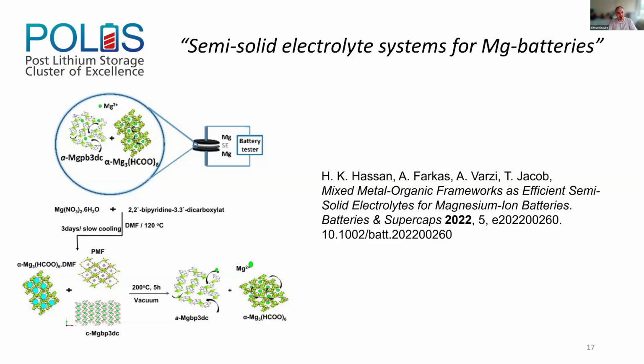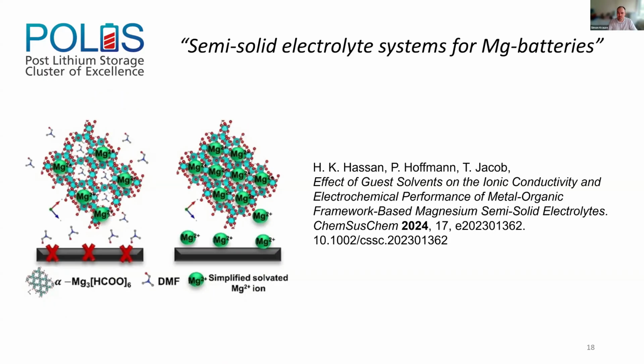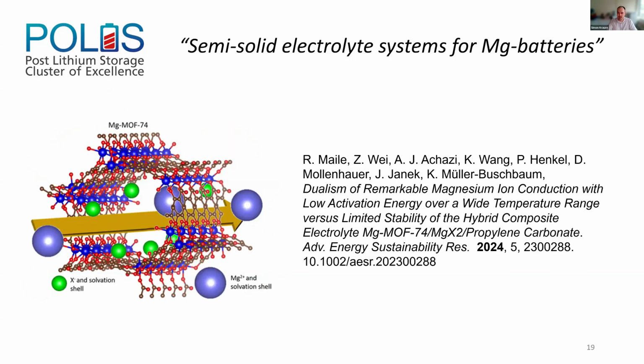Now, utilizing metal organic frameworks, which have been known for years, even before the term was coined, based on very simplistic formate systems, they feature very small ligand systems and now allow, in the combination of mixing different MOF components, to establish electrolyte systems with extremely high ionic mobilities. This research was extended by further tuning the MOF structure and its incorporation of different guest species and magnesium ion composites to further tune the properties of these electrolyte systems.